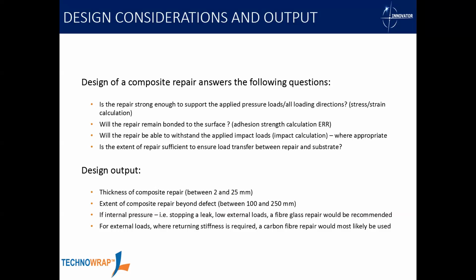Depending on what sort of loads we're seeing, what we're actually trying to fix, we get the material that we want to do the repair with. So as Shona went through before, you've either got the fiberglass, the UK cloth, you've got one of the carbon fiber choices, the SRS cloth or the high pressure pipeline repair system, which is a unidirectional carbon fiber. Generally, where there's external loads, where stiffness is a key driver of the repair solution, we'd use the carbon fiber, simply because the Young's modulus of the carbon fiber is that much higher than the fiberglass.